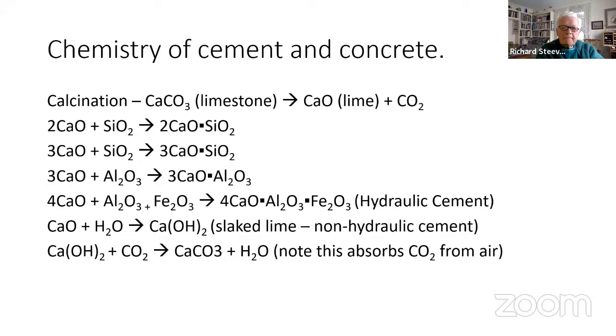So this is the chemistry behind cement and concrete, and this is in part what Richard's getting to. To make cement, and in particular Portland cement, you take limestone, which is calcium carbonate, CaCO3, and you heat it up in a kiln. It drives off the CO2, the carbon dioxide, and leaves you with lime, which is simply calcium oxide. And then you combine that lime with silicon dioxide, which is sand.